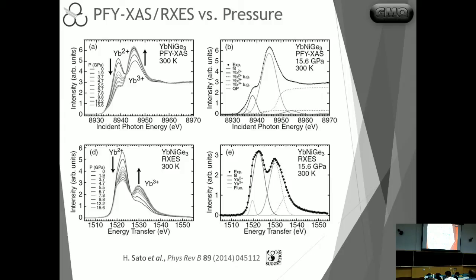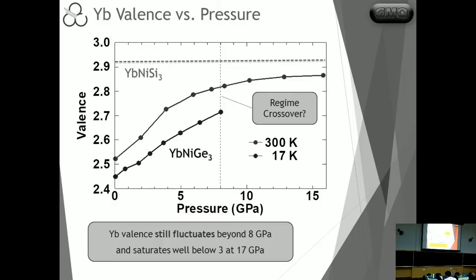When we look at the change in the PFY as a function of pressure, you can really see the ytterbium 2+ signature going down and the ytterbium 3+ signature going up for the germanide. Then by fitting all of these as a function of temperature and of pressure, we can produce final results like this. So where we were able to get thus far was to show that as a function of pressure, the germanide increases gradually up to where it comes close to where we expect the quantum critical point to be. And from then on, my collaborators believe that there's a regime crossover here.